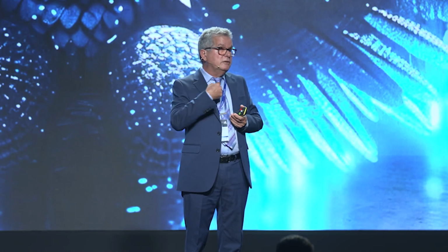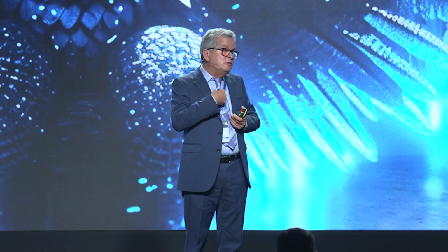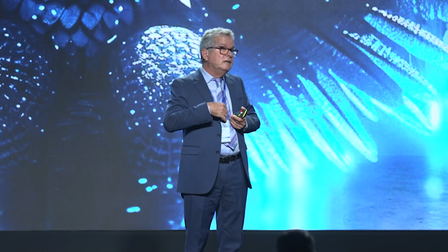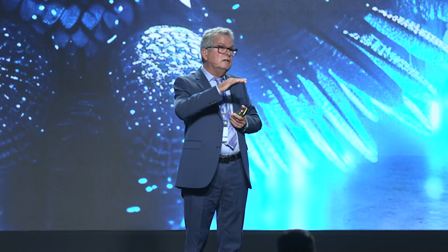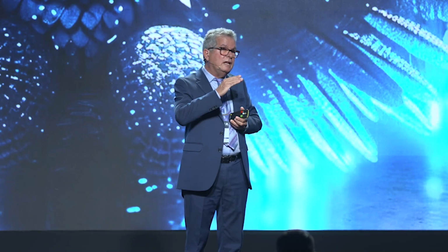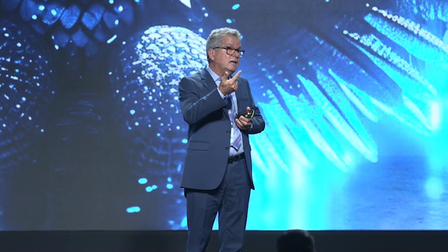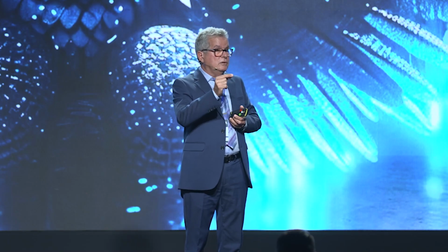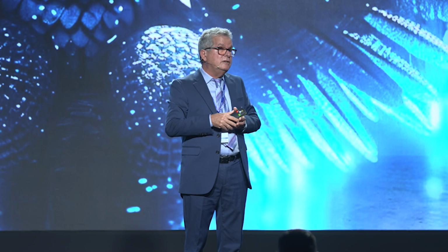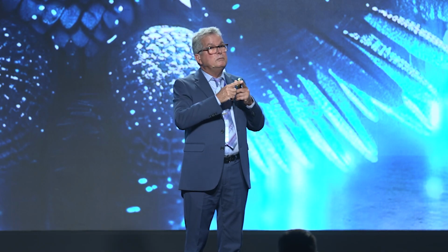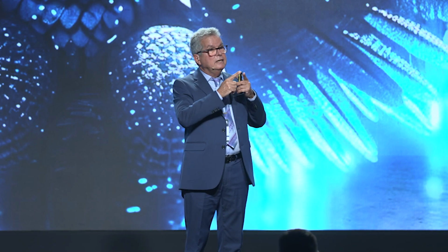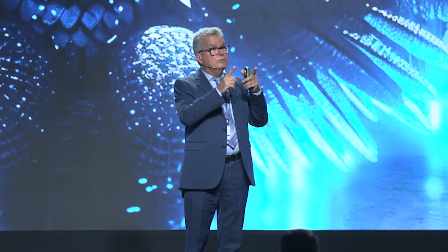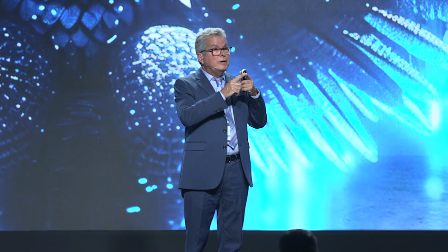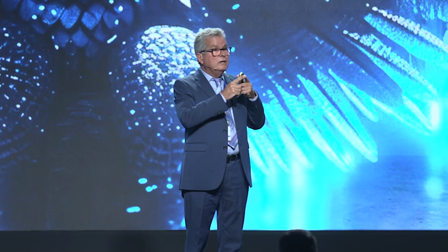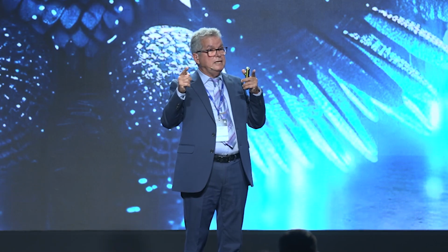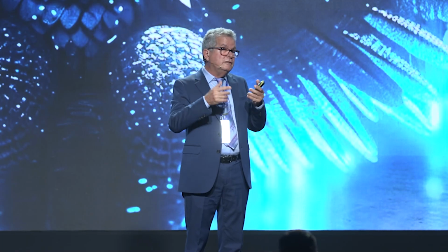And when you use this material and these admixtures, I am using them from all of the companies, you don't see any problem in rheology. You can have the same water to cement ratio. You only have to use a little bit more plasticizer. And also, one of the main problems we had with the calcined clays was the slump retention. The time was very short. It was less than 1 hour. So right now, I can tell you that we are producing concrete where you can have up to 3 hours of slump retention, which for the ready-mix industry is ideal.